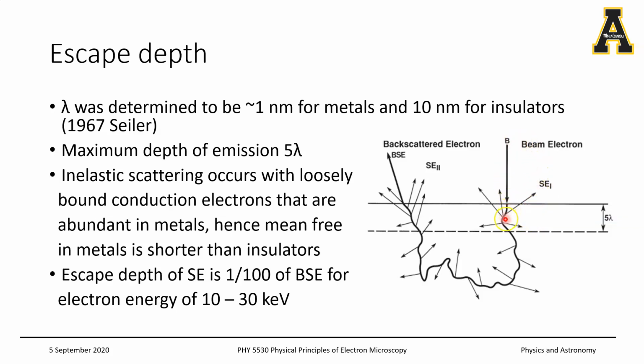And this incident beam then further travels down into the interaction volume. It undergoes several elastic or inelastic scattering. If it is elastic, it makes its way all the way up and it's gone. But if it is inelastic, it undergoes multiple scattering processes that is determined by the mean free path and also by, if you remember the Bethe equation, the energy lost per unit translation within the interaction volume. So all that comes into play here, and eventually some of them make their way out, right?